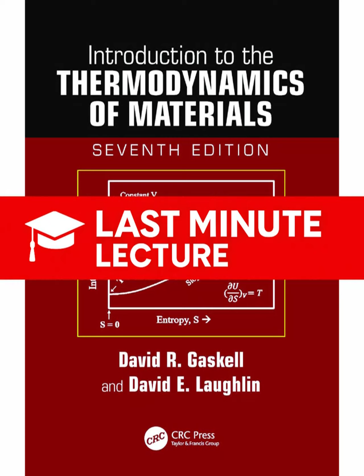It does. And we use these relations to derive what are called the TdS equations. These are pivotal because they let us calculate changes in entropy using measurable things like heat capacities and expansion coefficients. The second TdS equation is probably the most useful one since it uses T and P as the variables. It is. It says TdS equals Cp dT minus T times the partial of V with respect to T at constant P, all times dP. And that shows us exactly how entropy changes with temperature through the heat capacity term and how it changes with pressure through that thermal expansion term.